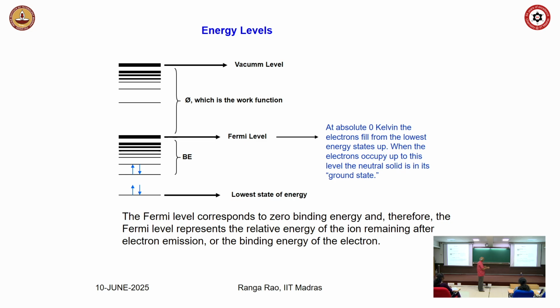So up to here you have filled the electrons, and if these are sitting in the core level, they have a very specific binding energy. But then as you keep going here, this becomes like a band, delocalized kind of. This region is the valence level region. So the Fermi level corresponds to zero binding energy. So that means you call this the zero binding energy highest, and then from there you measure the binding energy below.